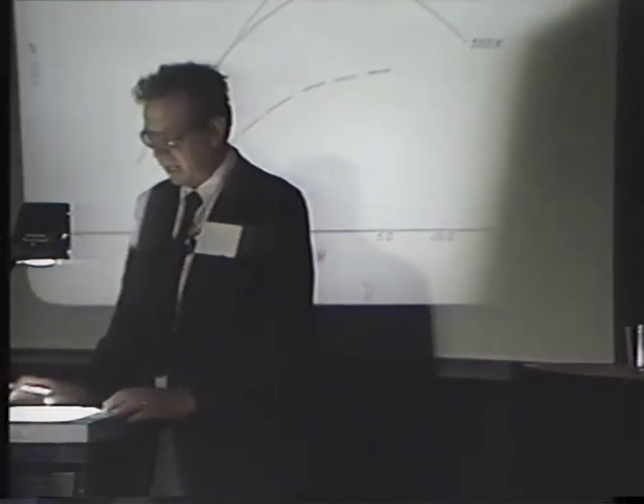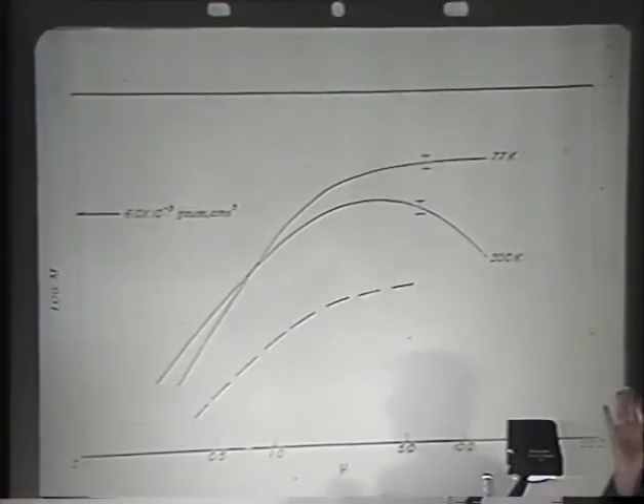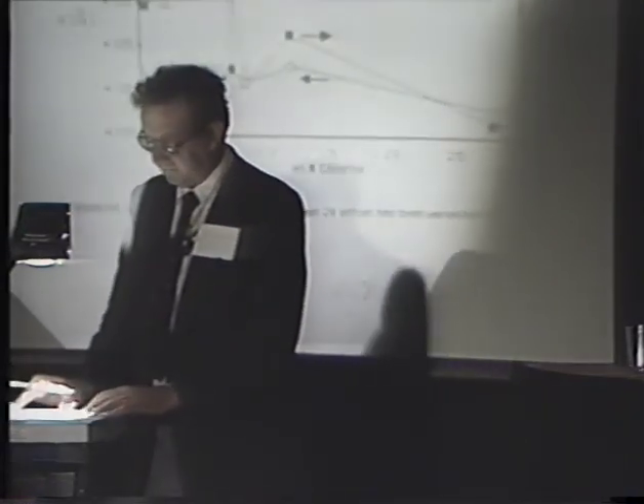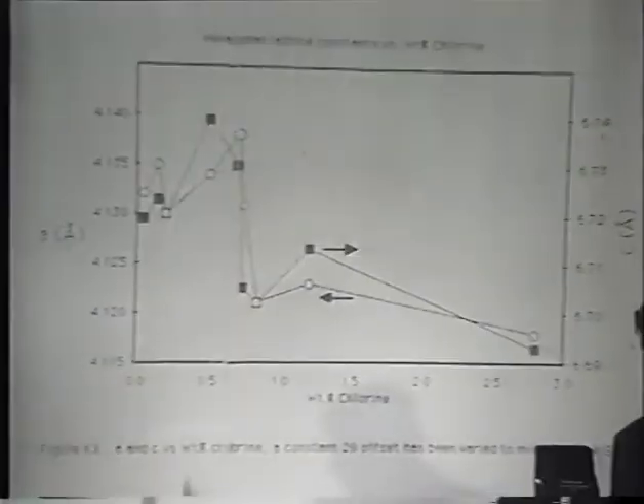In the paramagnetic state, we get behavior that looks like this. And I believe this is something which is kind of unique to this system and may well be found in some of the perovskite systems at higher temperatures. And then finally, our evidence for the metastable Wurtzite phase is this, that doping it with chlorine, we find that the lattice parameters show a discontinuity at exactly 0.78% chlorine. And what we believe is that when the pressure is released, the sodium chloride phase tries to become Wurtzite. It doesn't know whether it belongs in this phase or this phase, and there are a large number of soft phonons present. Thank you.